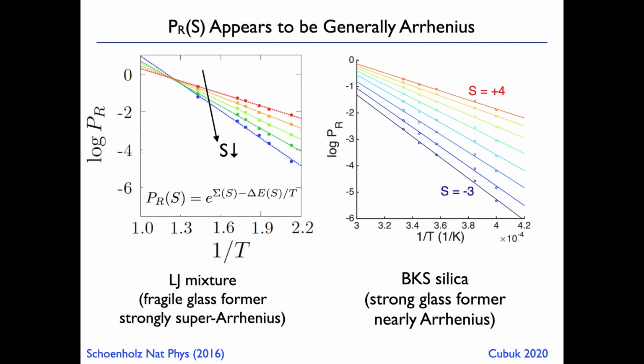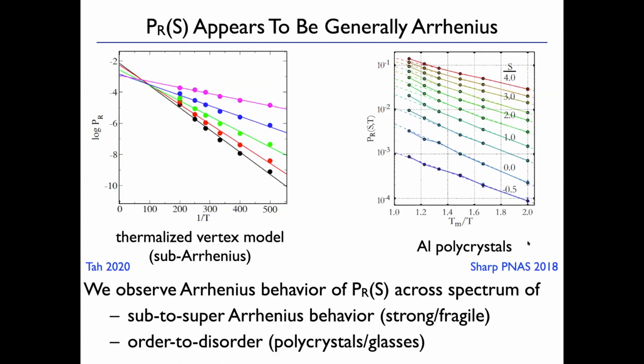this property that the probability of rearranging at a given softness is Arrhenius, which appears to be generally true? So this is the Lennard-Jones mixture, which I just showed you. We also looked at a strong glass former, silica, a network glass. And again, the log of the probability of rearranging versus 1 over temperature is a straight line, so this is Arrhenius too. These are systems that have nearly Arrhenius behavior.